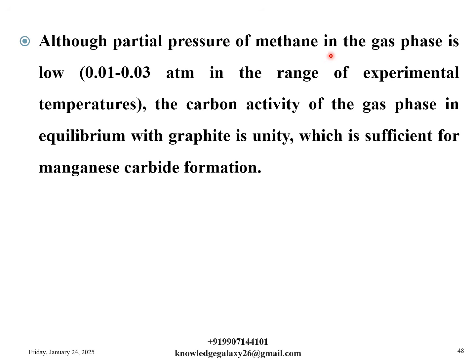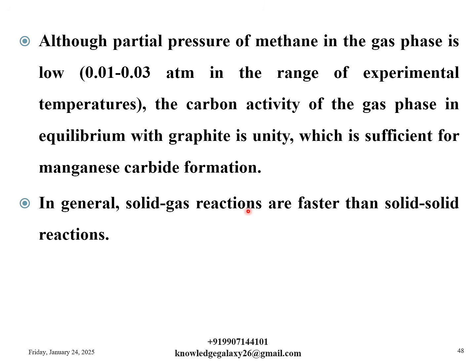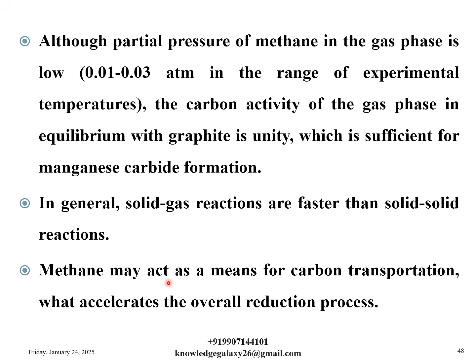Although partial pressure of methane in the gas phase is low, that is 0.01 to 0.03 atmosphere in the range of experimental temperatures, the carbon activity of the gas phase in equilibrium with graphite is unity, which is sufficient for manganese carbide formation. In general, solid gas reactions are faster than solid-solid reactions. Methane may act as a means for carbon transportation, which accelerates the overall reduction processes. I again repeat this: methane may act as a means for carbon transportation, which accelerates the overall reduction processes.